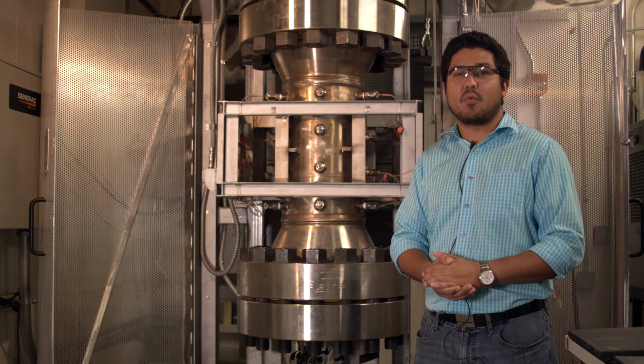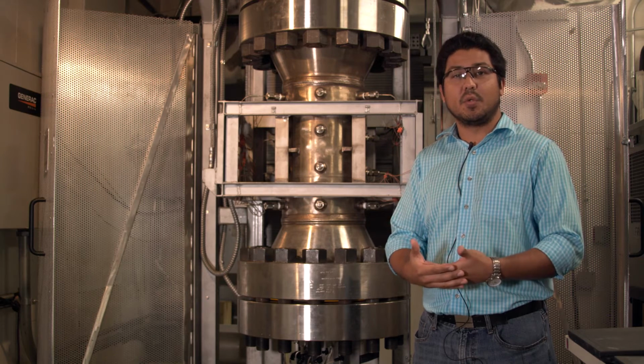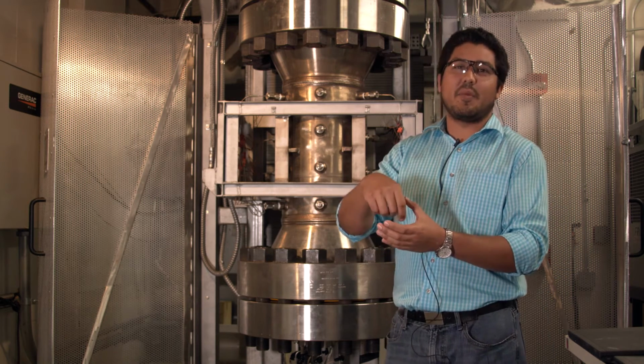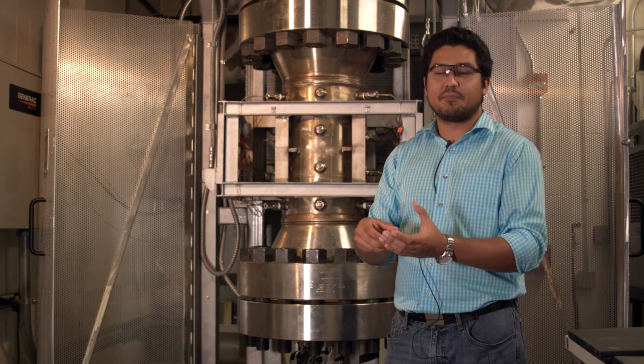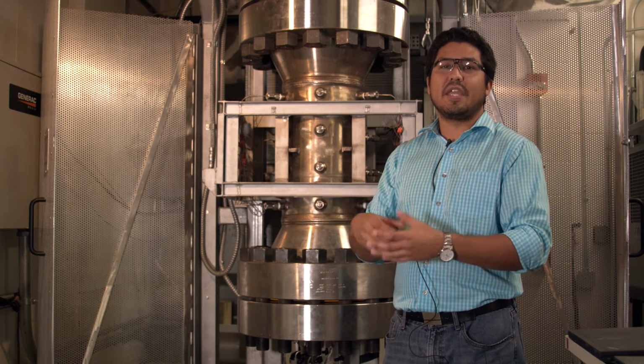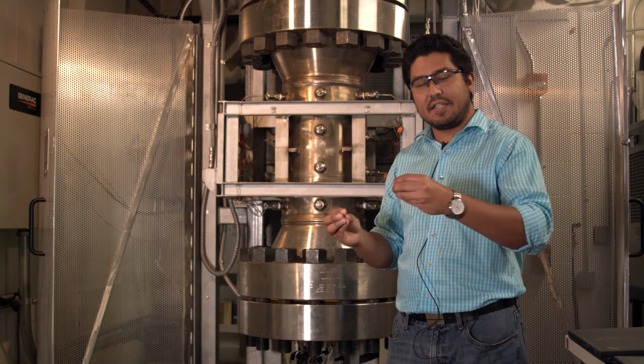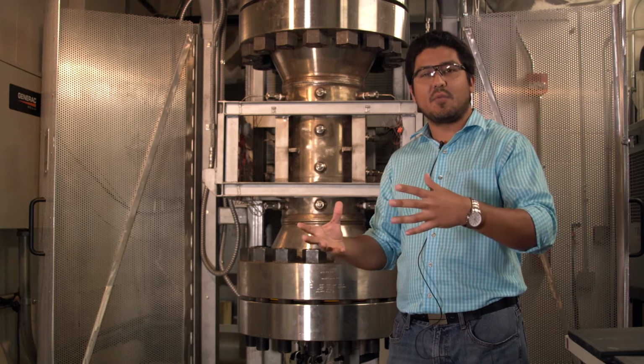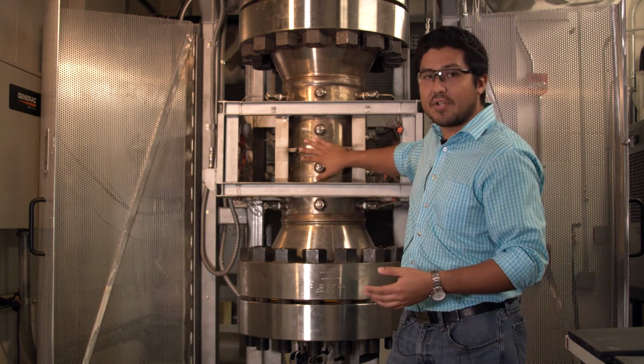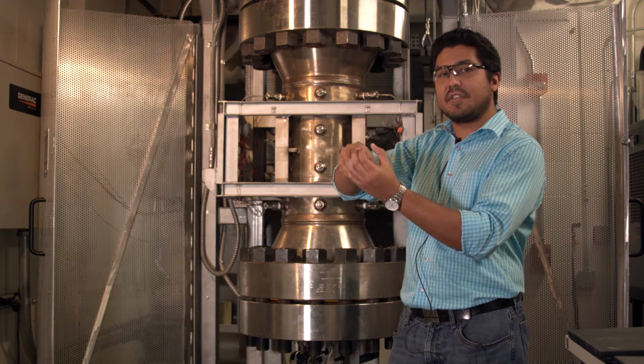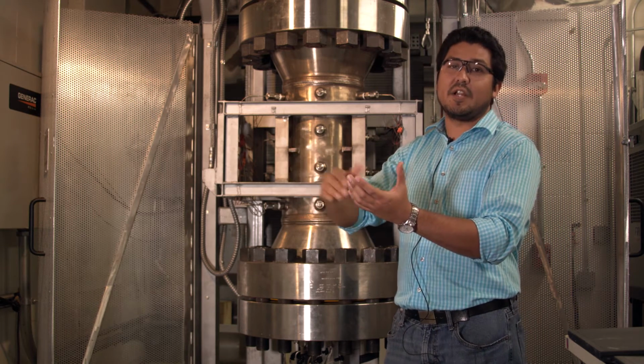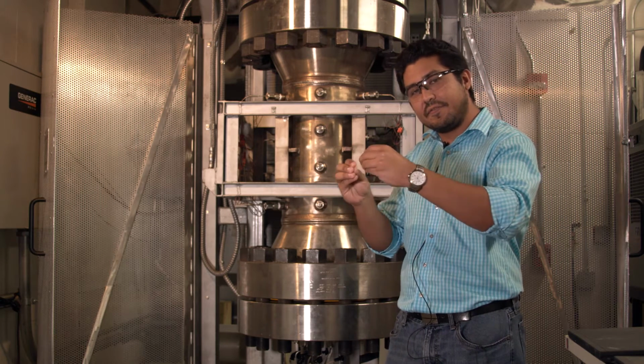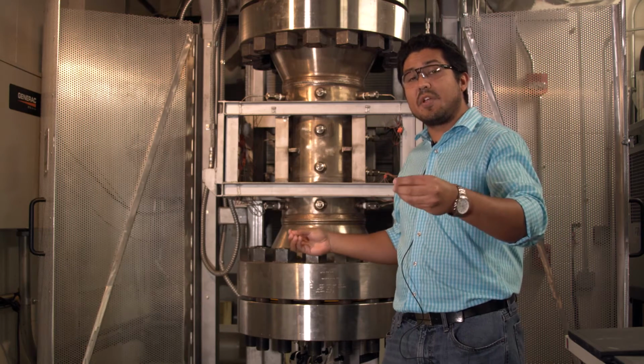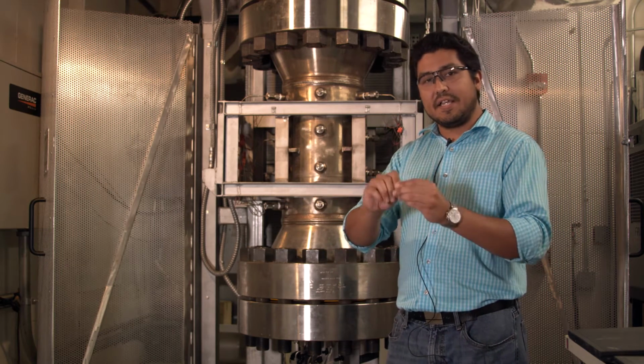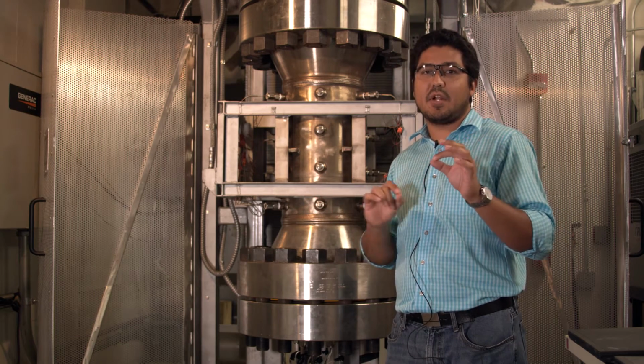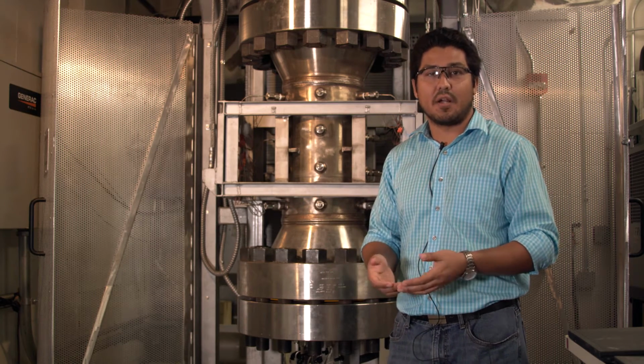And the reason we do this is for the processing of, like I said, BSCCO-2212, wherein you start with silver wires with micron-sized tubes in them. You fill them with powder, and the issue with heat treating 2212 is that gas that's inside of those tubes will expand when you heat them up. So the idea of putting overpressure around those wires is that you compress that and make sure that gas can't expand. Now the temperature excursion up to 900 degrees actually melts that powder into these filaments, these long strain filaments. And then what you get out of the heat treatment, once we cool back down, is this wire with long ceramic strands, which is the superconductor, which is the superconducting part of 2212.